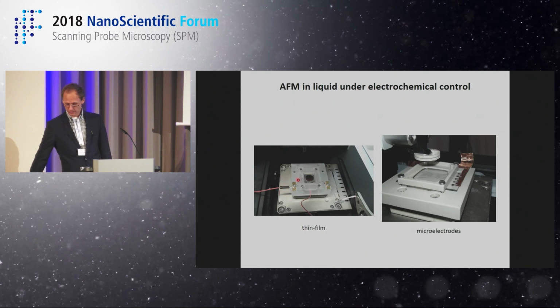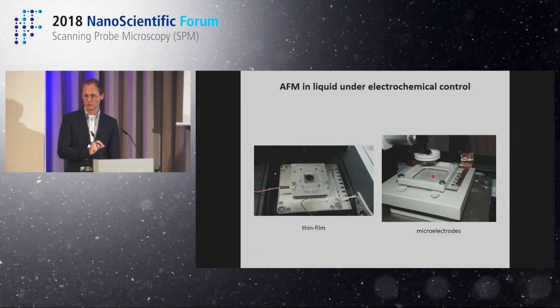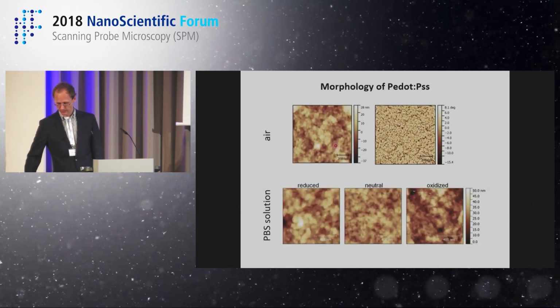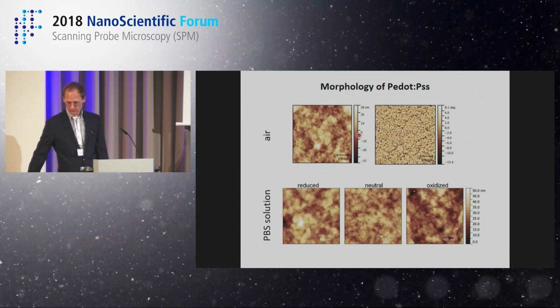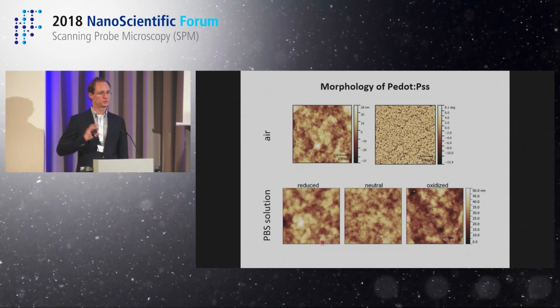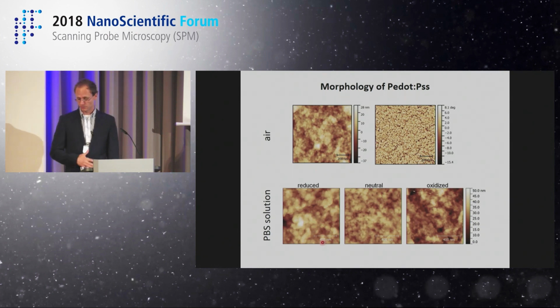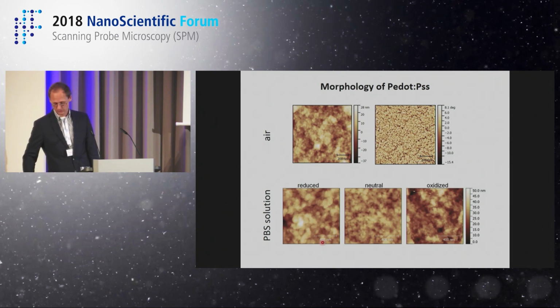So the first one is just a very large polymer film that you have here in the center, where you can just measure a macroscopic thin film, or you can also contact just micro electrodes and see what's happening at a smaller electrode scale. Okay, going to morphology, at the end, this is not so interesting. In air it's nice because, let's say, with tapping mode, you can nicely observe these nanocomposite morphology. When you go into liquid, it gets a bit more difficult to observe the nanophase separation in the material. However, what you see is that basically the morphology is not so different as a function of, let's say, the doping level of your material. So the amount of charges does not really have an impact on the topography that you observe in liquid. Okay, so that's for sure not what the cells are feeling, what is kind of making a difference.